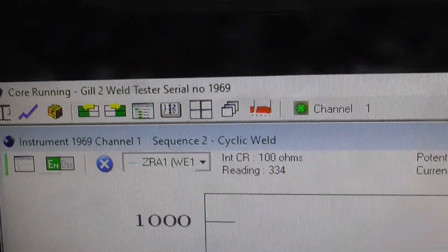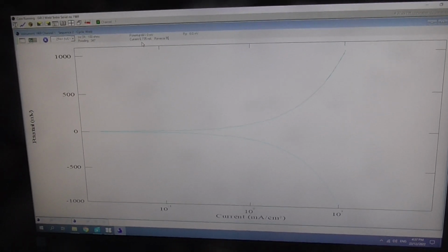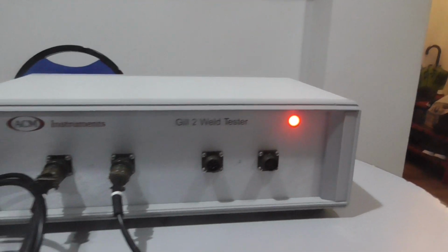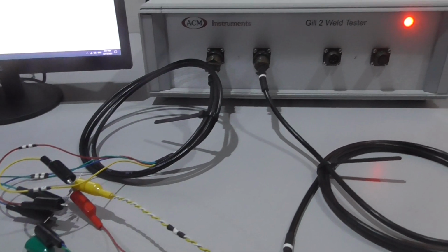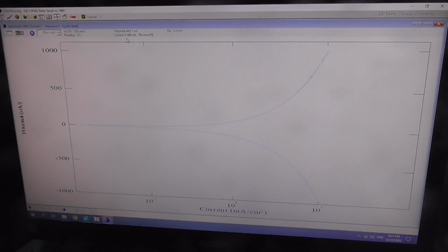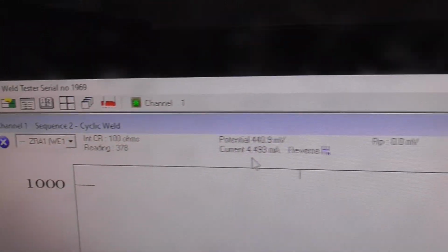So actually, welds pose a lot of particular problems. Each weld is a complex galvanic couple made of parent metal such as pipeline, a weld metal, and an area of heat affected metal. Under many circumstances, the bulk of the anodic dissolution is within the heat affected zone. This very thin anode and large cathode of parent metal is the worst possible case, rapidly leading to failure. Conventional electrochemical testing, in which a sample of the weld is immersed and used as a working electrode, will only reveal a low overall net rate, not the high rate in the heat affected zone.